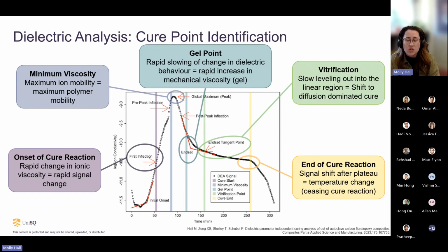This is one that has been suggested in literature previously, but we extended that analysis to all 5 parameters with good success. And this one's quite well accepted, that at your maximum signal, you have the maximum ion mobility, and that's correlated to the maximum polymer mobility. The next one is the gel point, which I've correlated to that end set after that global maxima or minima. And the reason for this is the way I've defined gel point in this work is the rapid increase in your mechanical viscosity of the material system. There's several ways that others have defined gel point, and maybe some of the other proposed correlation methods that were previously in literature aligned to one of those definitions, but this is the definition that I've used, and it aligned quite well to that rapid slowing of that dielectric signal due to that rapid change in your mechanical viscosity.